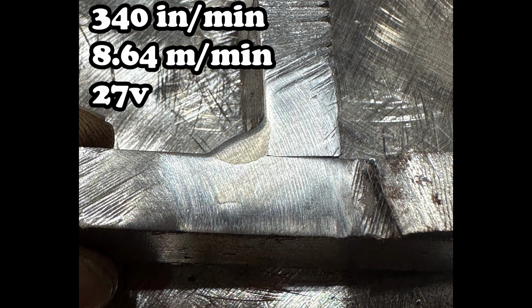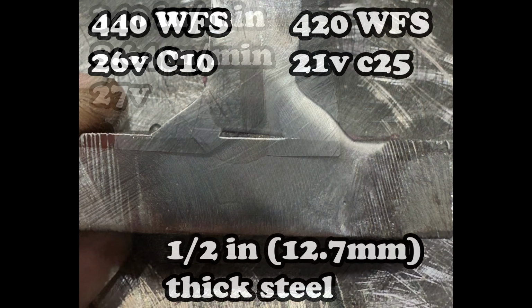And I've done a ton of cut and etches with this product, and it just doesn't penetrate very well. And I think universally that's going to be the case with this, even at higher settings, because this is .045 wire. It might get a little bit better, but again, not a very high penetration in the root process. Now, when we compare it to spray arc, that's significantly different. So let's look at that.